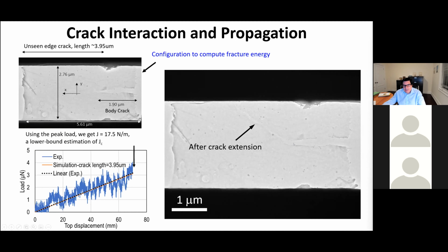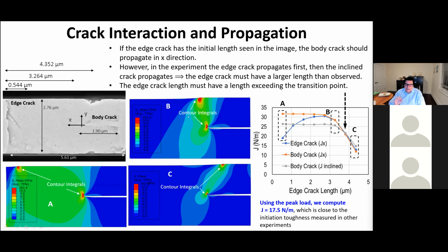But due to the challenges in transfer and dealing with such small and extremely thin samples, we had another crack here, an edge crack. During the cycling nothing happened here, but this crack probably was propagating. So we did some fracture mechanics to see if we could infer the toughness of the crack that propagated at the end of the experiment. Fracture mechanics is very good at doing this because we model the geometry with the edge crack, the body crack, and different scenarios with different edge crack lengths.